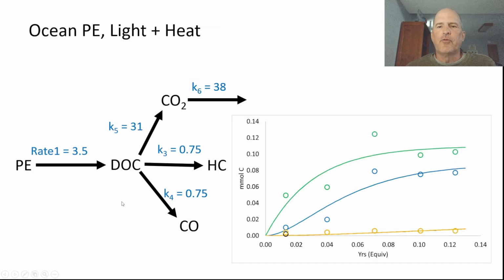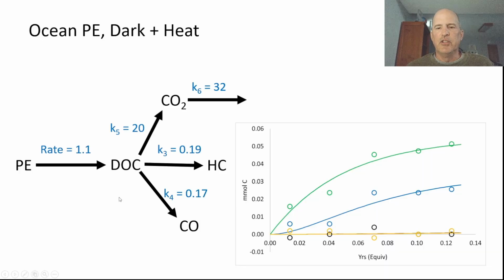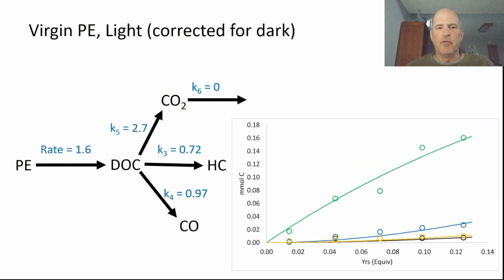So I'm going to flash through these pretty quickly. You can do the same thing for the ocean polyethylene. This is both light plus heat. This is in the dark, so this is the control experiment for the ocean polyethylene. And then I also did a fit for the virgin polyethylene, corrected for the dark. And this one also has a CO2 escape rate constant of 0. So you would expect a good linear fit.